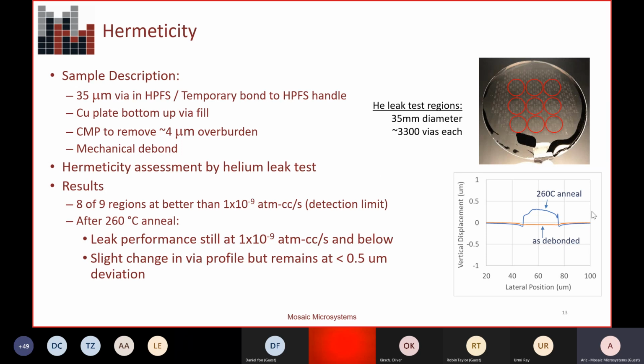I will say that when you do an anneal, what I'm showing here on the bottom right is the planarity after a 260 degrees C anneal. You do see a little bit of a piston, about a quarter of a micron, so 250 nanometers. So that would need to be managed depending on your application, but still that would be a very quick planarization if you need better than 250 nanometers.